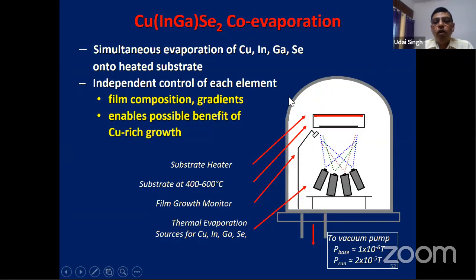Now, if you are using co-evaporation, there are 4 sources for the 4 different materials. It's thermal evaporation. You have a film growth monitor, so you can monitor the rate. The substrate is kept here, and on top of that you can have a substrate heater, which can work at 400, 500 degrees, whatever is required. So you have independent control of each element, film composition gradients, and the possible benefit of copper-rich growth. So you can vary these different parameters.